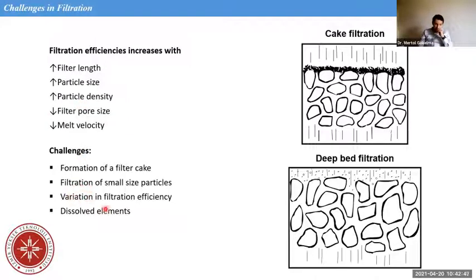And another challenge is variation in filtration efficiency. What I mean is, let's think that you do filtration with this filter for 6 hours. The filtration efficiency will not be the same in the first hour as in the last hour. There will be a variation in filtration efficiency. That is one of the challenges in filtration. And in some works, it is even published that in ceramic foam filters, the filtration efficiency can vary from 25% to 95%. It's a very high range of variation.